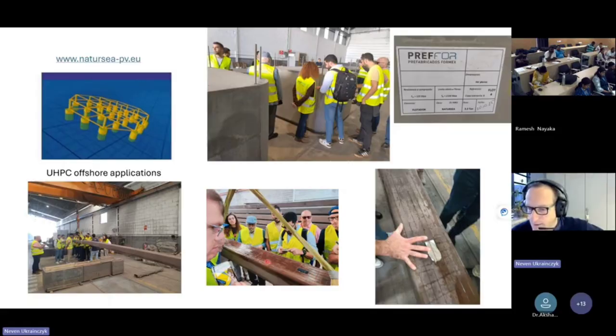First you can hear them, and then we also saw them, because when you wet it, you can see where it's drying. So the water goes into the cracks, capillary, and then you can easily see the cracks. You can measure how many cracks you have. And after, when you put it down, the water goes out. So it's very, very interesting. You can see how the capillary water which went in then goes out. So you can see in this 20 centimeters how many cracks you have.